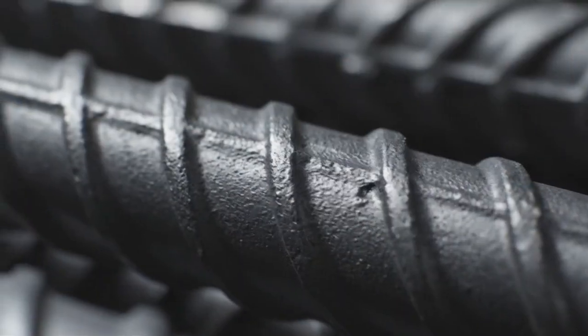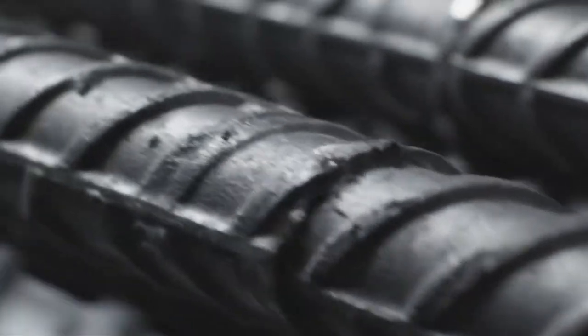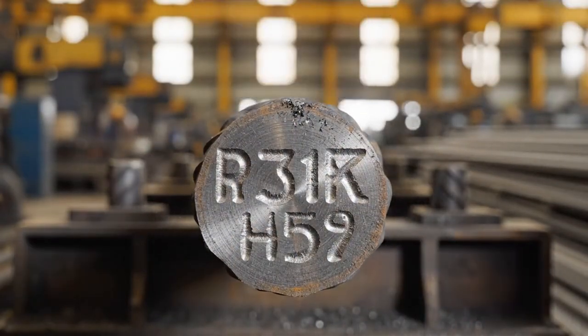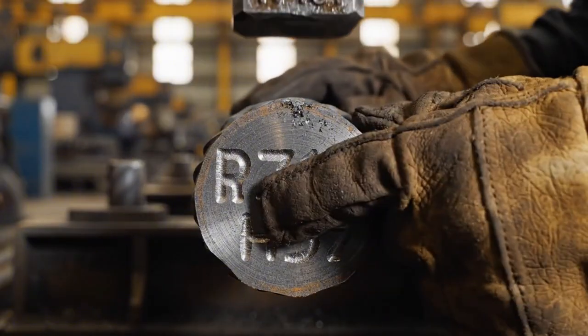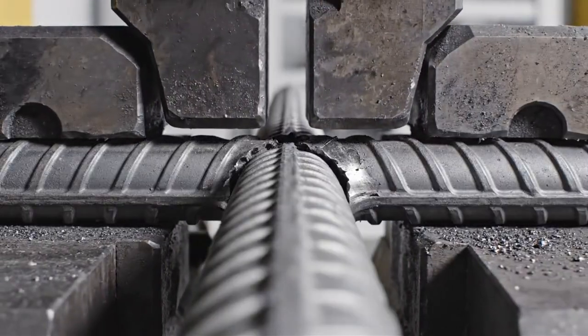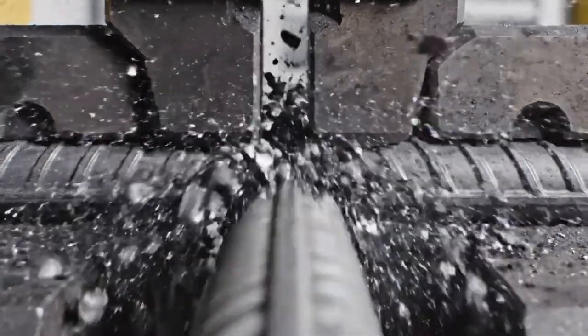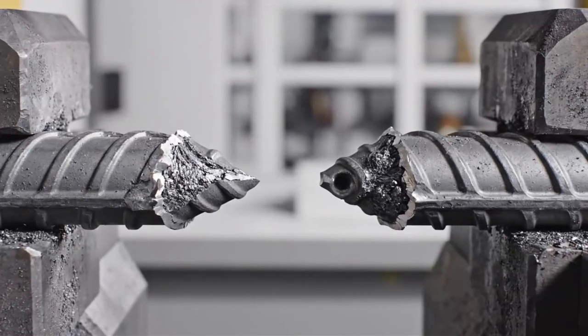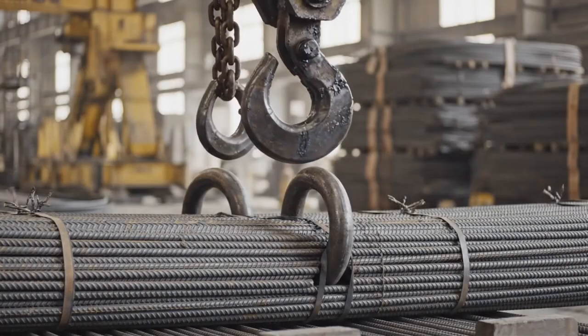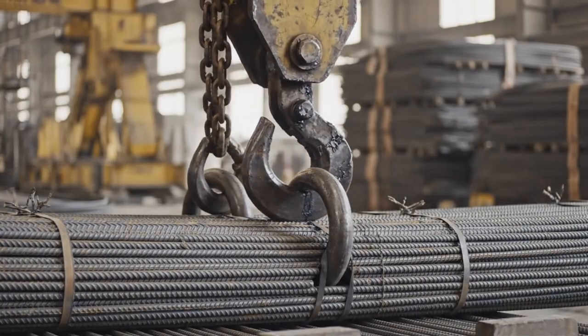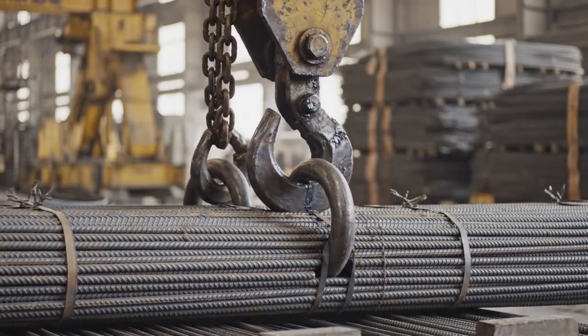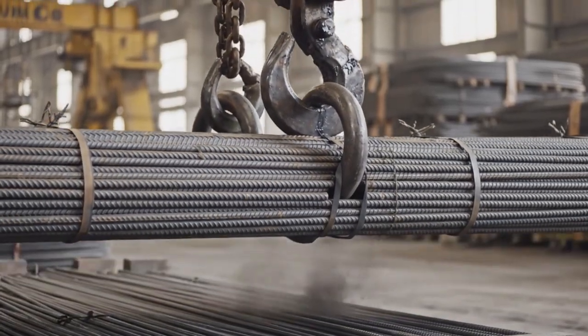The macro view highlights the rough, gritty texture and the precision of the helical ribs, crucial for the bond with concrete. The rebar reaches its ultimate tensile strength, causing necking and then a sudden, violent rupture at the failure point. With the hook securely fastened, the finished rebar bundles are hoisted, ready for the next stage of transport.